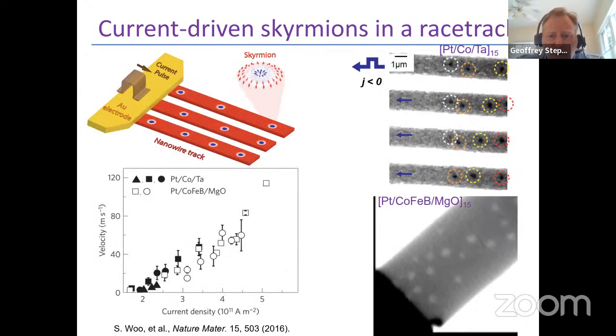In these kinds of structures, it's been shown experimentally by ours and a number of groups that at least larger skyrmions, bubble-like skyrmions, can be driven in racetrack-like devices. This drive can be relatively reproducible, and the speeds can be relatively fast, on the order of 100 meters per second. And so this is desirable for devices. This is quite exciting for devices.